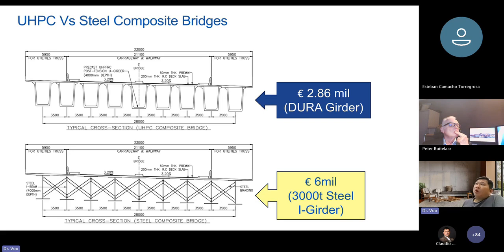And here's an example of the comparison of the steel composite bridge versus the UHPC composite bridge. For the steel girder in this project, if I use the equivalent amount of steel to take the same loading, the amount of steel I needed is about 3,000 tons, and it would cost around 6 million euro at that time. And our UHPC girders, which are nine girders, cost less than 3 million euro. So you can see that immediately there is more than 50% cost saving.